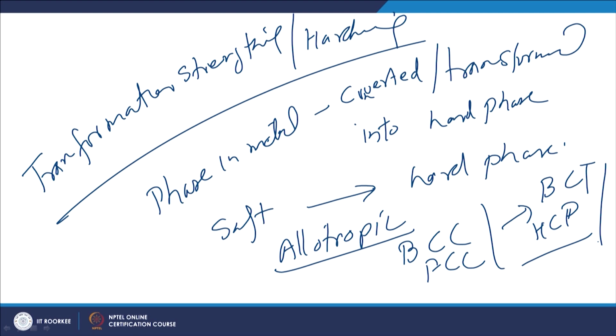in a very controlled way they may have the BCT structure or HCP structure. So, the controlled transformation of the softer phases into the hard phases leads to the increase in strength of the metal, and when these are processed during welding, some such transformations take place, both from hard to soft or soft to hard phases.